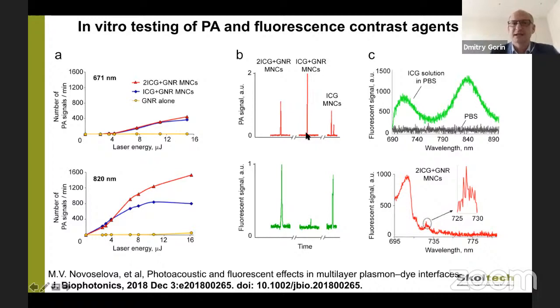Why did it happen? Because for this type of object, it is necessary to take into account not only the amount of light absorber, but also mechanical properties. And if you encapsulate albumin-indocyanine conjugate, we increase the thickness of the shell, and we change the mechanical properties. But you see, our expectation about quenching is working. But for the next application, for in vivo, we selected the first sample. Why the first sample? Because we have an acceptable level of optoacoustic signal, and we also have a fluorescence signal.